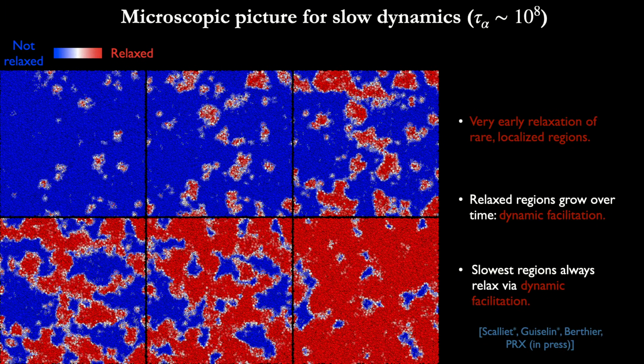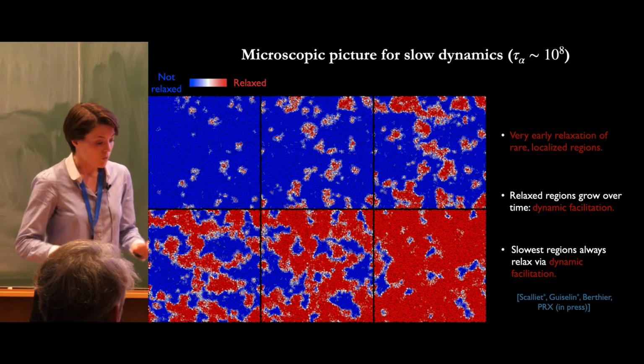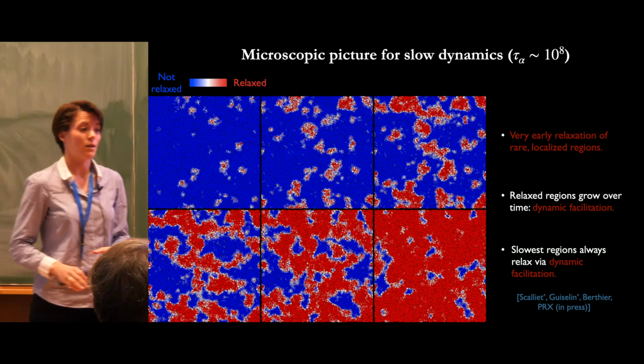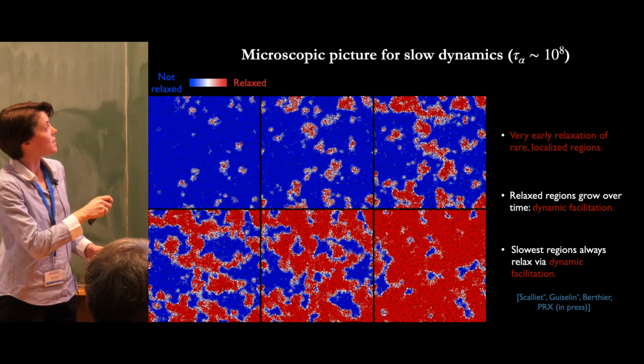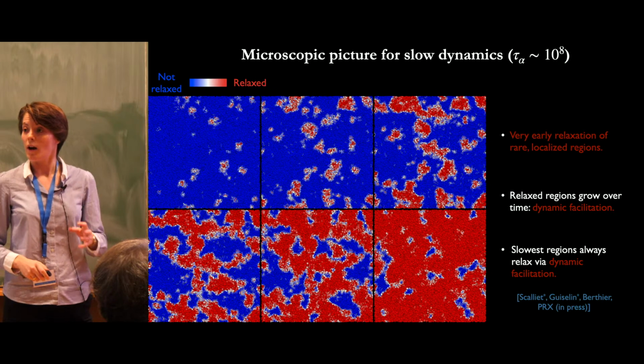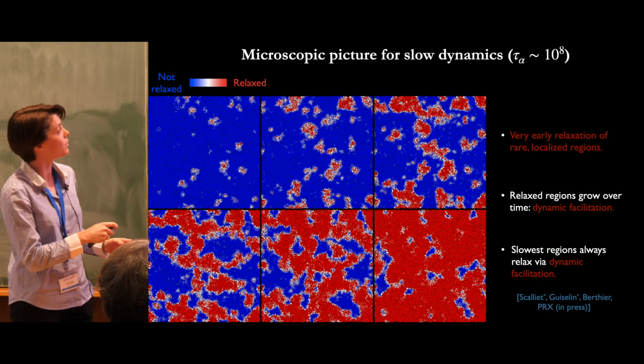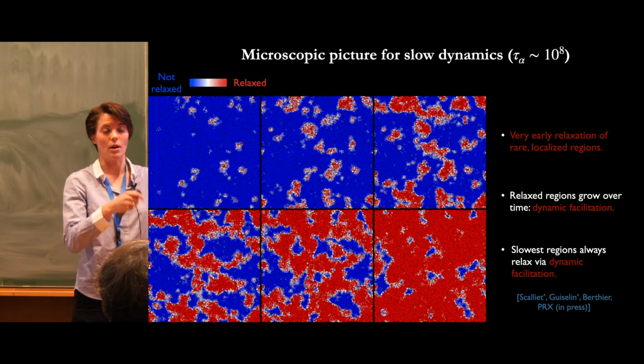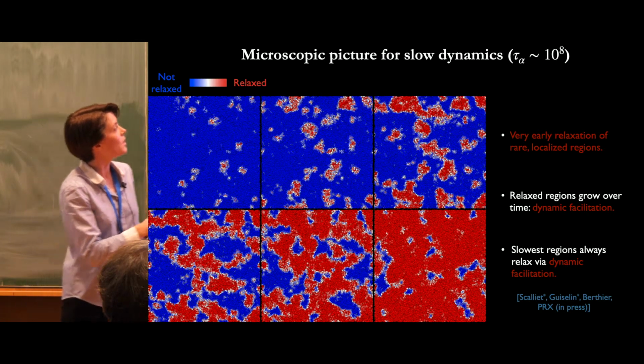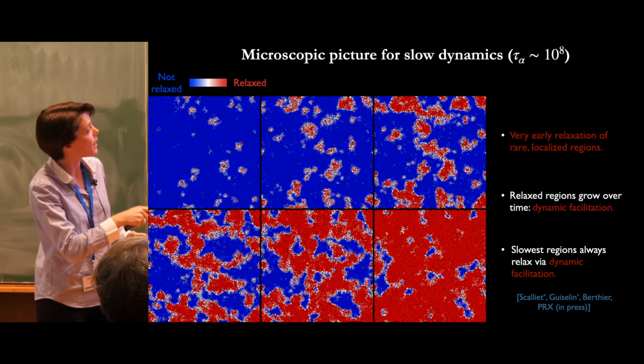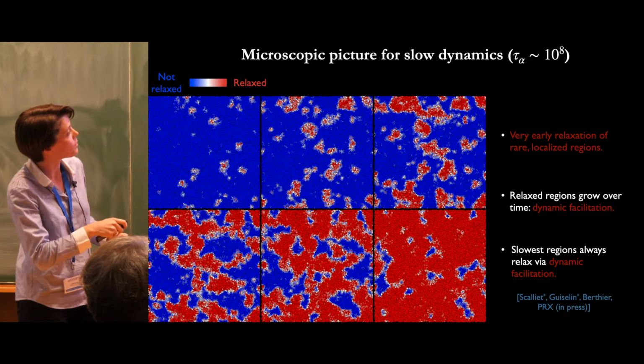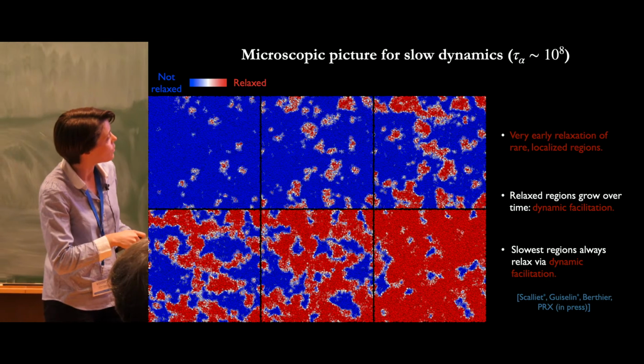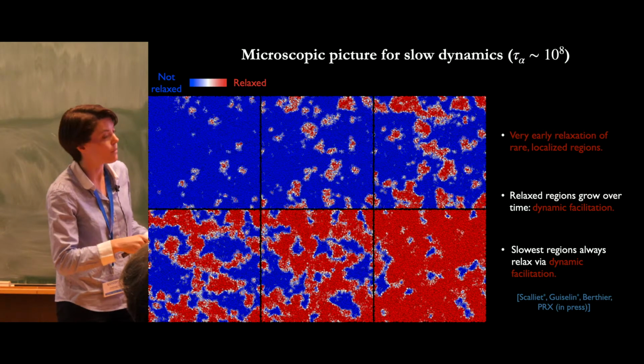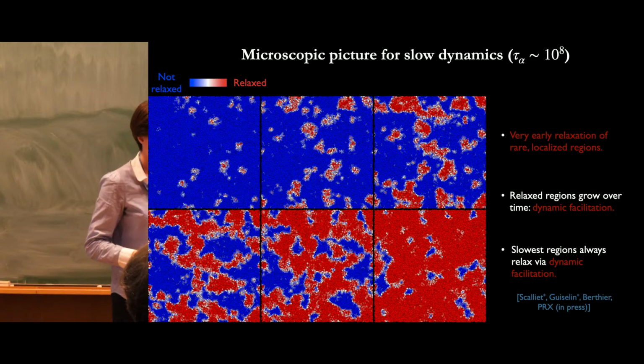Here is a summary of what we observe, going from short times to longer times. 2 tau alpha corresponds roughly to this snapshot here. What I will describe and quantify in the next slides is the following. Very early, much earlier than 2 tau alpha, we do have particles that have relaxed, corresponding to these red clusters here in which the particles have rearranged and lost their neighbors, hence appear in red. Then as time increases, these clusters grow in size, and eventually, at longer times, they start to merge, and the dynamics proceeds by the growth of these existing regions.